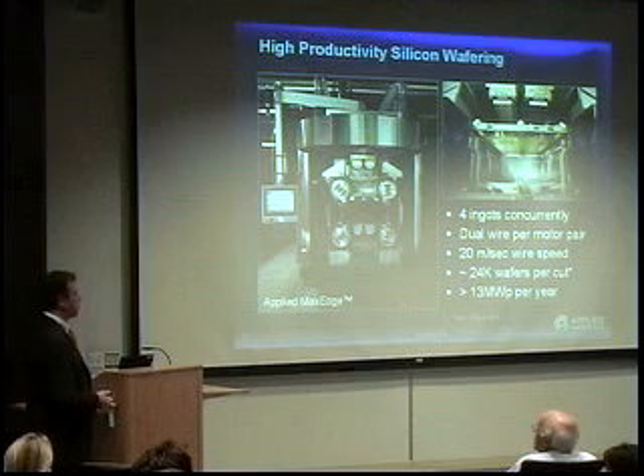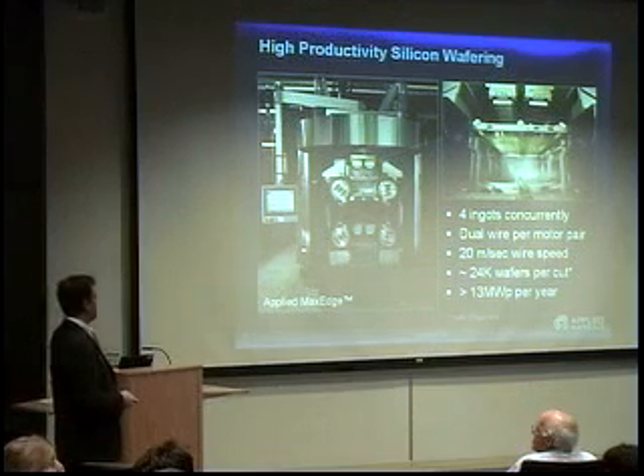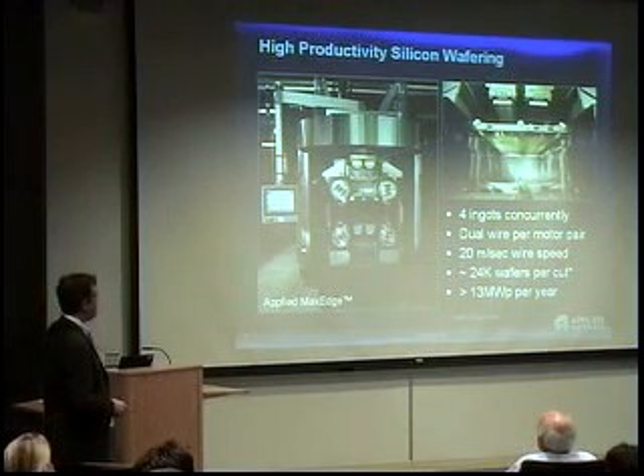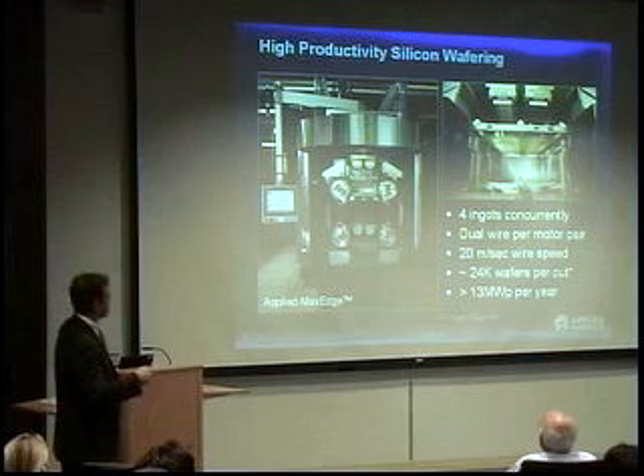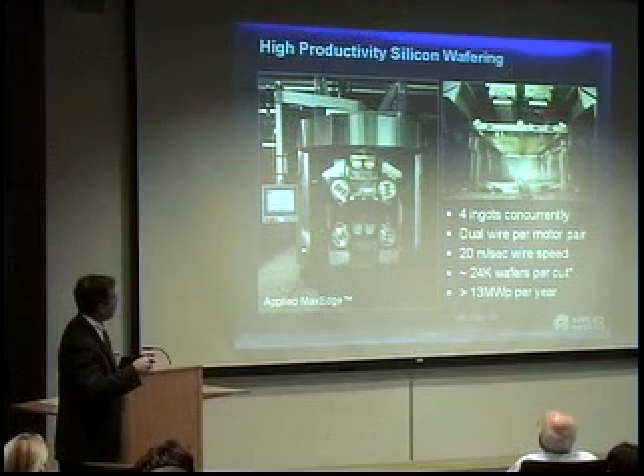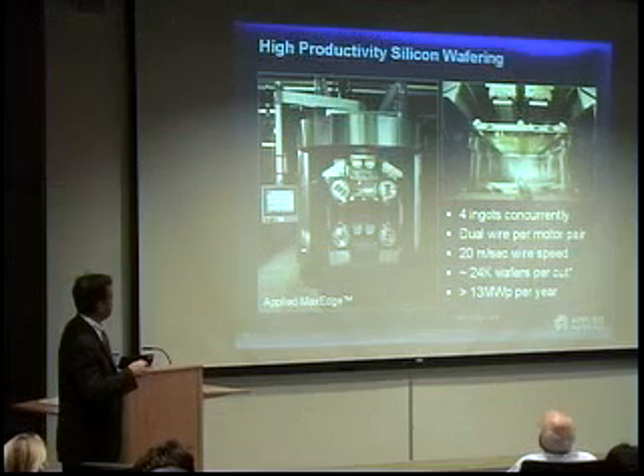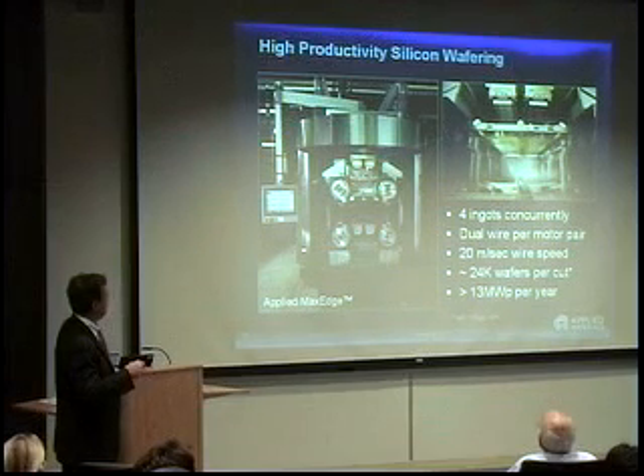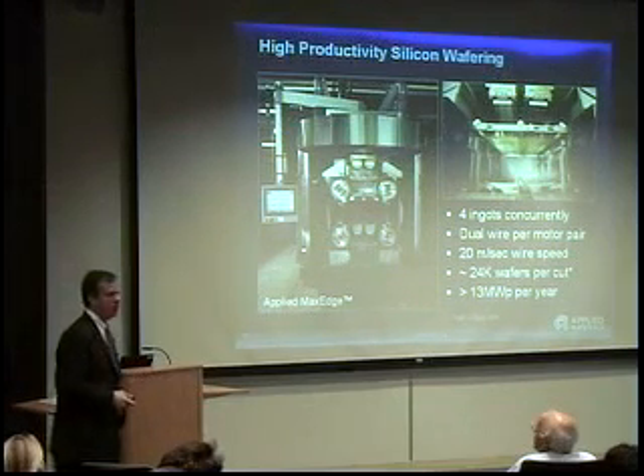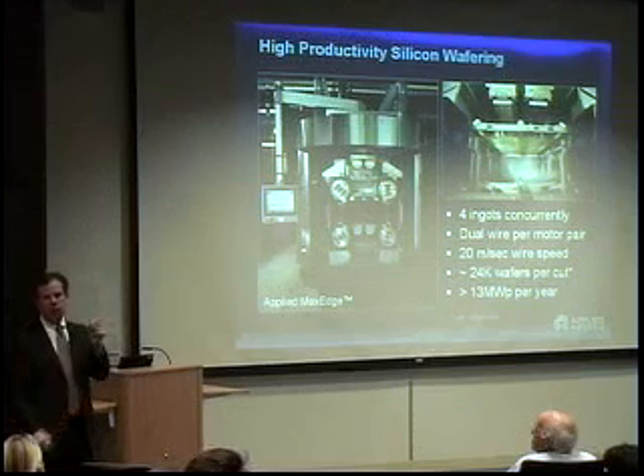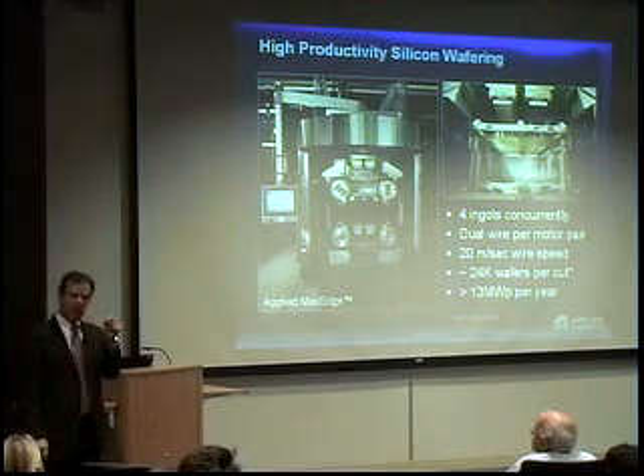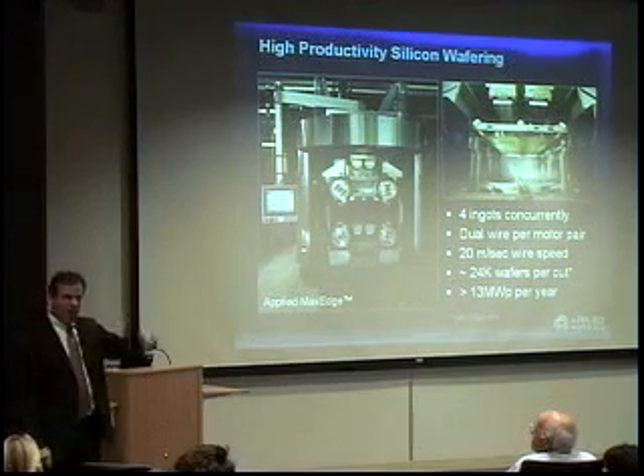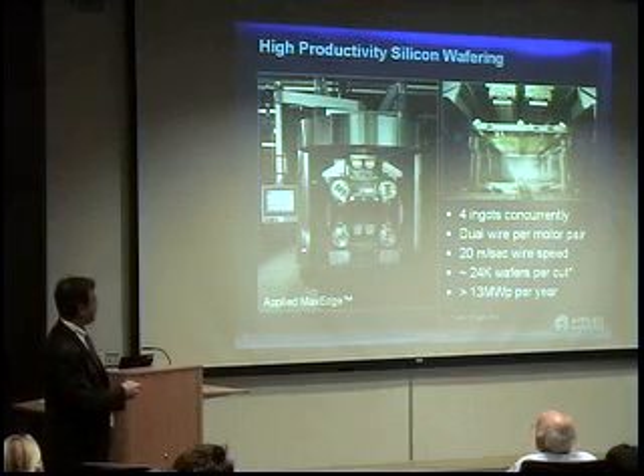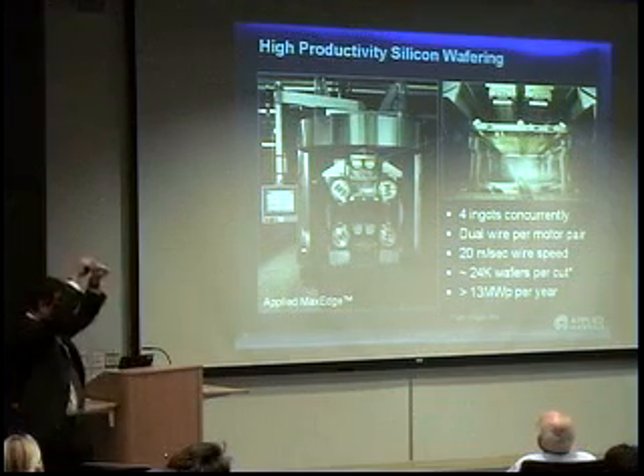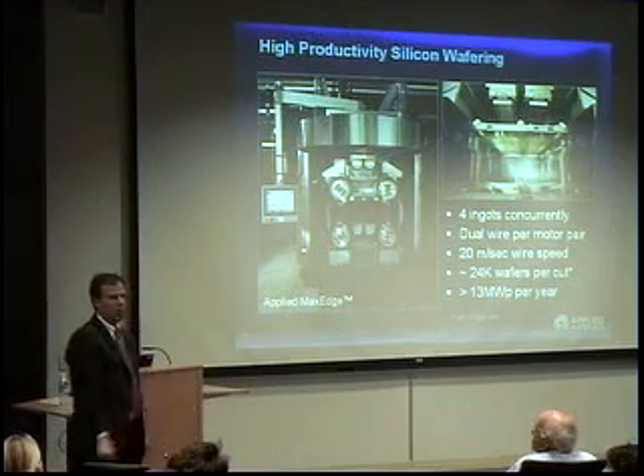So the first one is, how do we make these thin wafers? So this is a state-of-the-art wafering machine. What you see here are 4 blocks of silicon, 1, 2, 3, 4. They're going to go through a mesh of wires. Those wires are 100 microns or 120 microns thick. They run at kilometers per hour along this web. And we have a slurry, and you just push those ingots through.